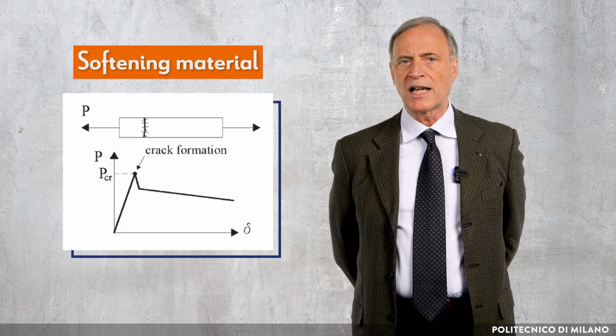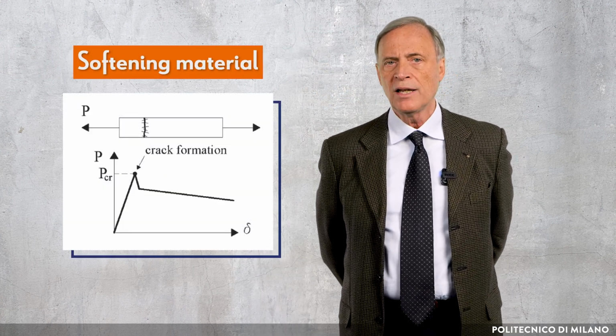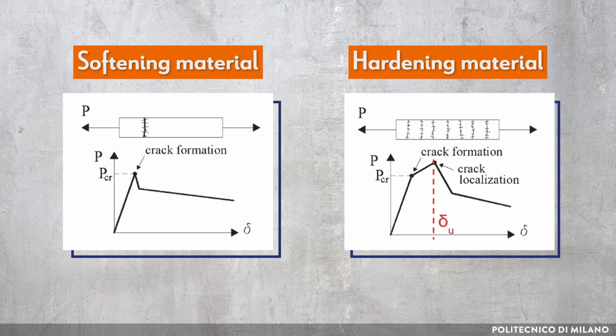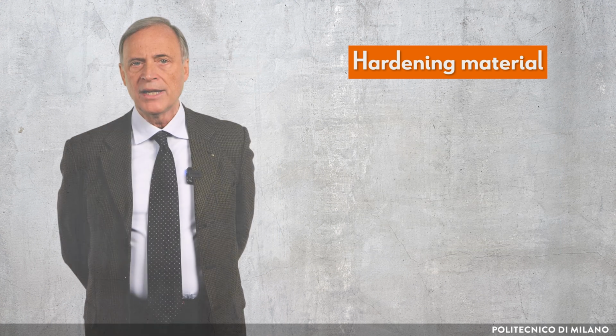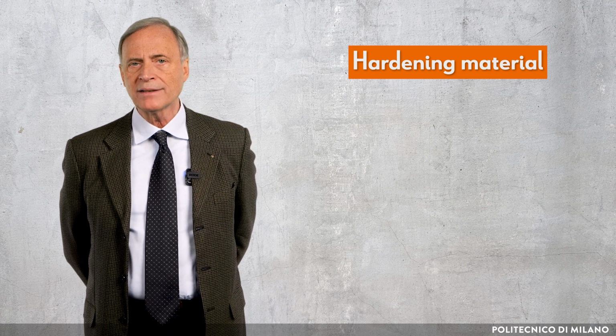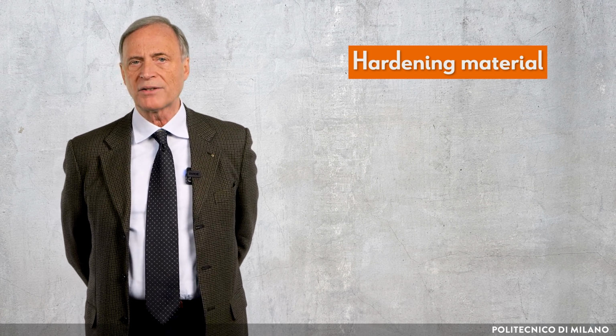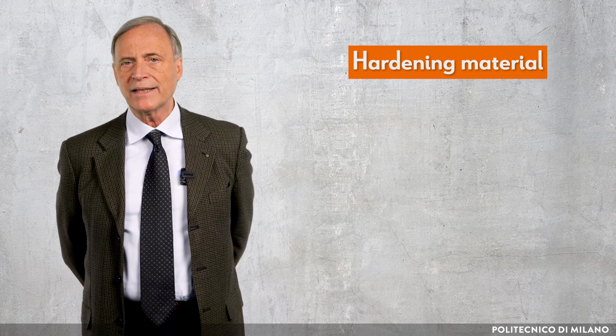According to the amount of fibers and to their effectiveness in the matrix, mainly depending on their aspect ratio, corresponding to the ratio between the fiber length and its equivalent diameter, their geometry, and the bond strength of the matrix, it is possible to obtain two main behaviors in uniaxial tension: a softening behavior characterized by only one crack formed in the weakest cross-section, or a hardening behavior with a second branch along which a progressive microcrack propagation takes place until a crack localizes and the following softening behavior takes place. The hardening materials available today in the market represent the most significant product obtained by the advanced products made available by chemistry in the 90s.